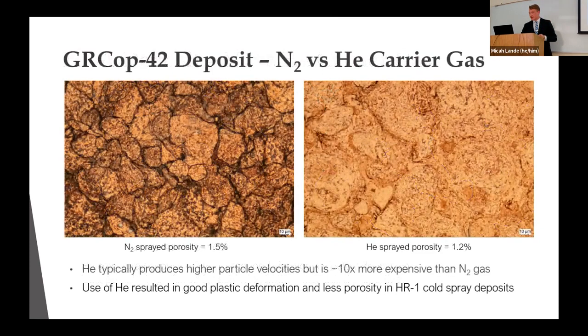And this exact same thing can be seen with our copper alloy, not quite to the same extent, just because our copper alloy, of course, being copper, is a little bit softer, so it deforms quite a lot better. But again, we see a lot fewer boundary lines between those individual particles. So again, that's just showing that the helium sprayed ones definitely are going to have a lot better properties. However, that does still come at the cost of using helium, which is about 10 times more expensive to use than nitrogen.